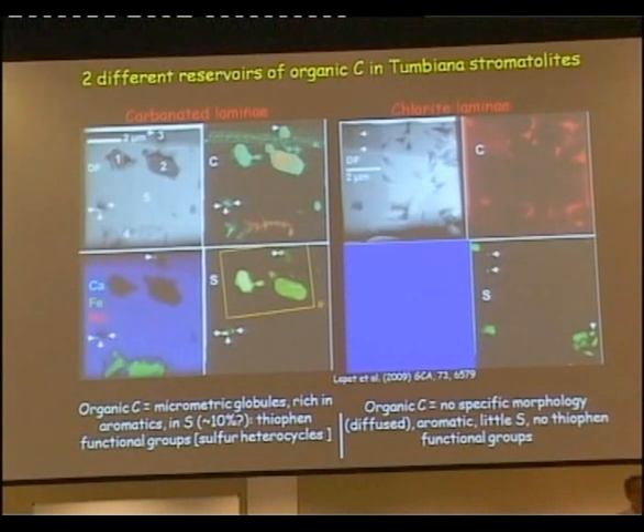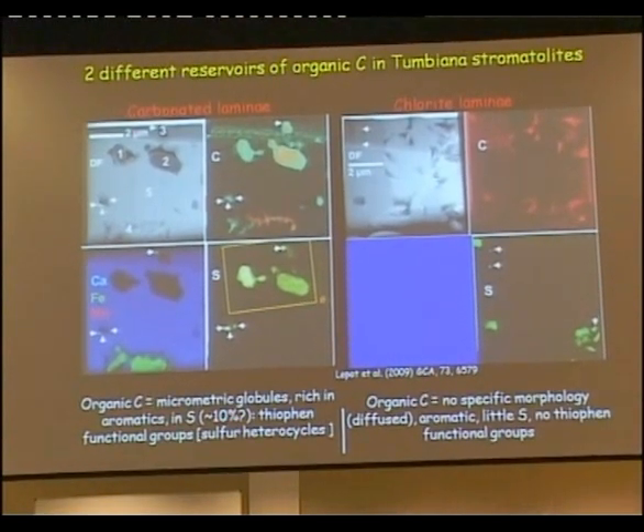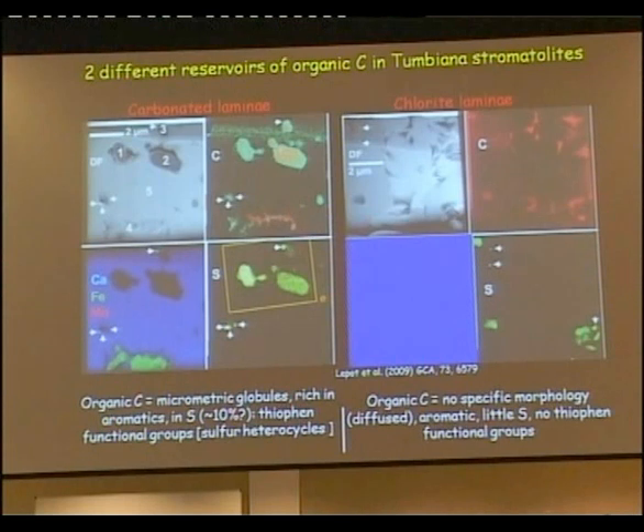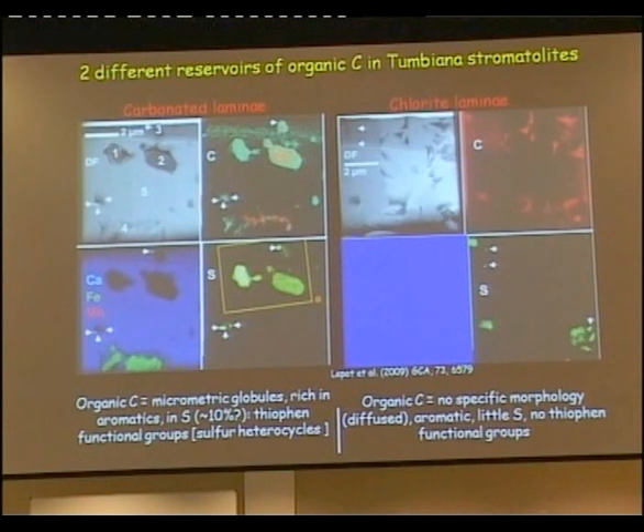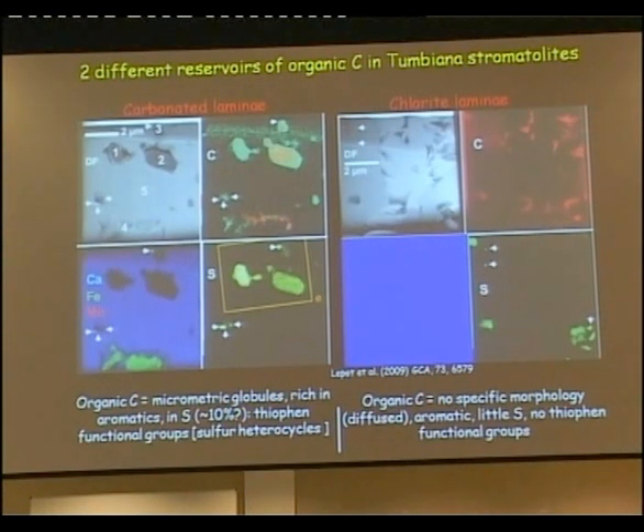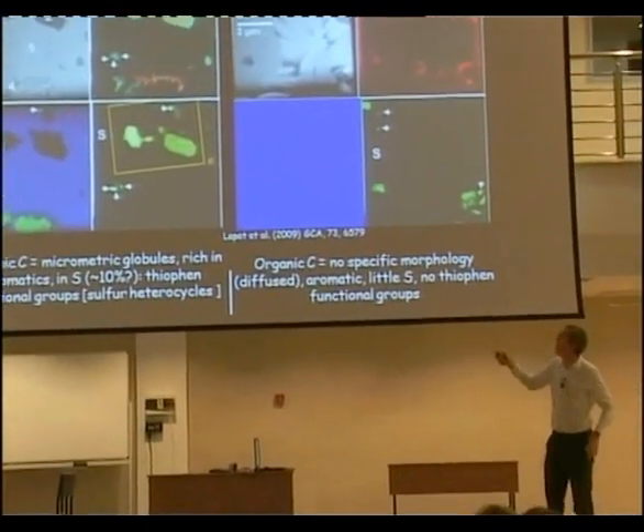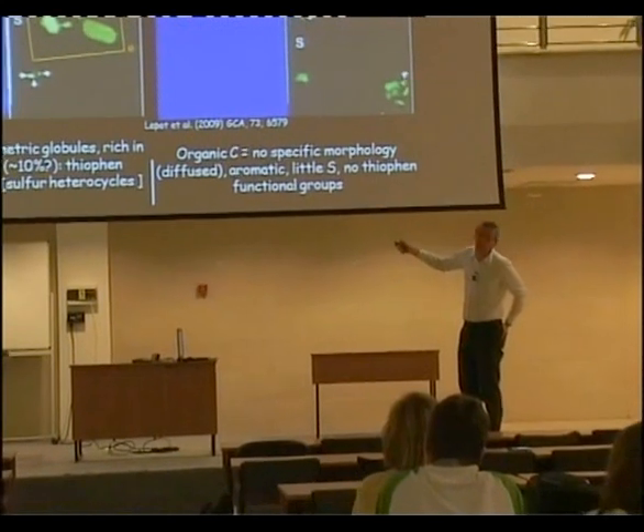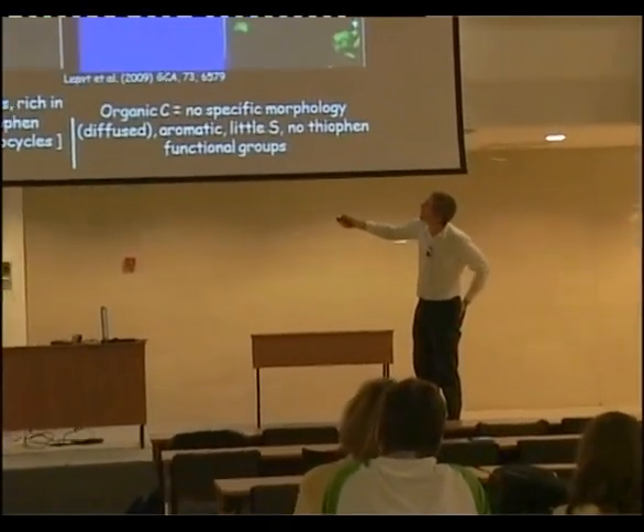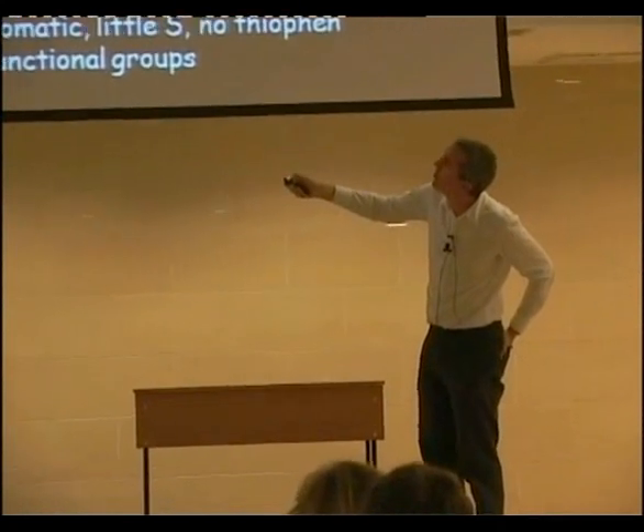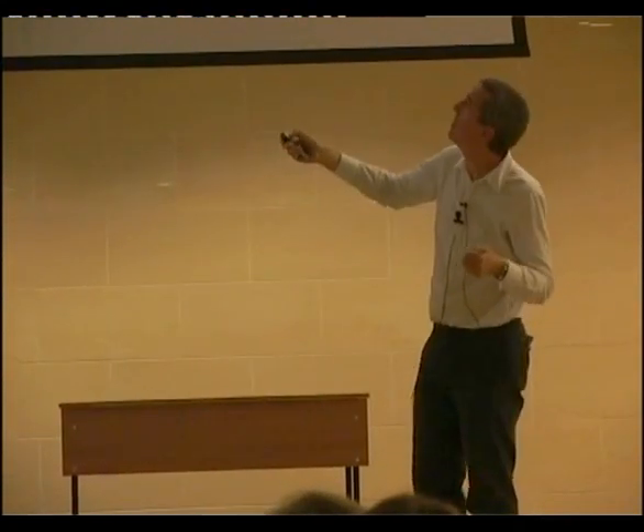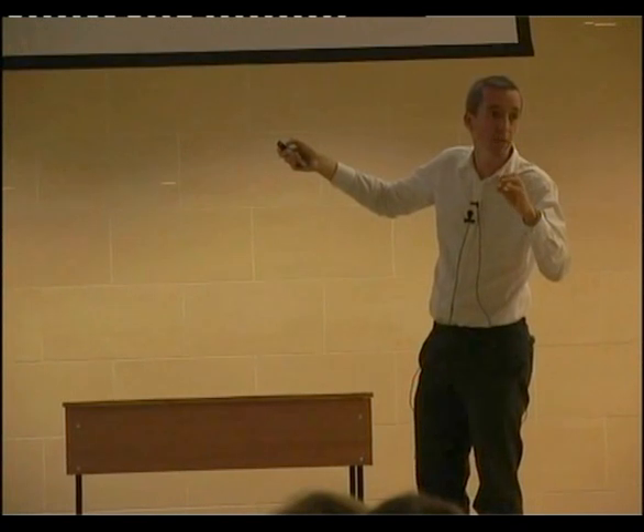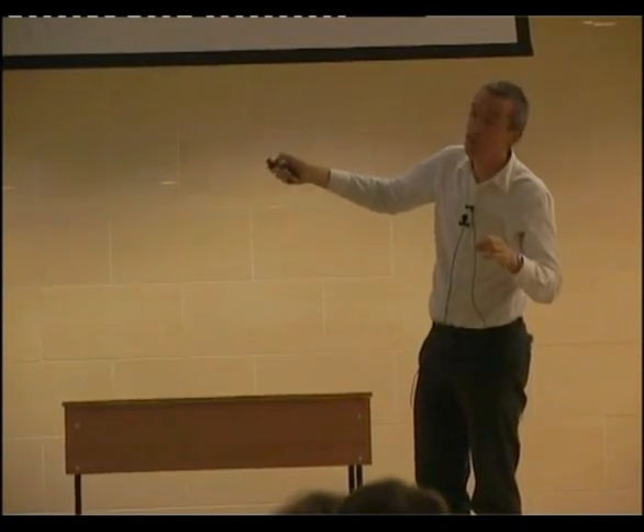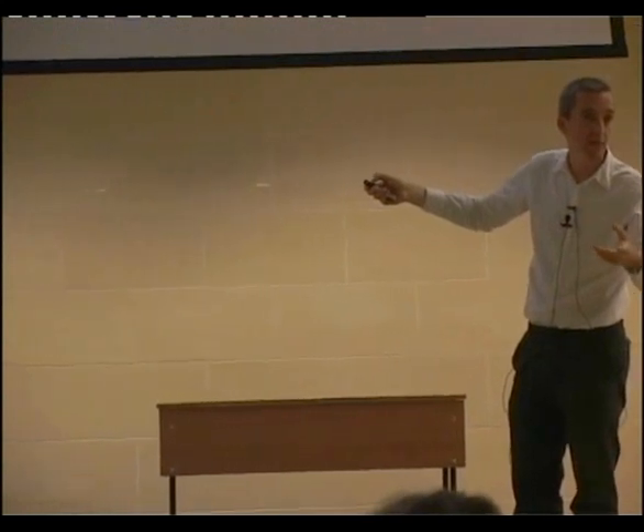So the first thing we do, we look at the sample by TEM, and we do EDX mapping. So we get the maps of major elements in the sample. And remember, the bright laminae are calcite, and the dark laminae are chlorite. So we first look at the carbonate laminae, the bright laminae, and this is how they look. In this laminae, we can see some globules, and these globules are made of organic carbon, plus sulfur. There's a lot of sulfur in this carbon.